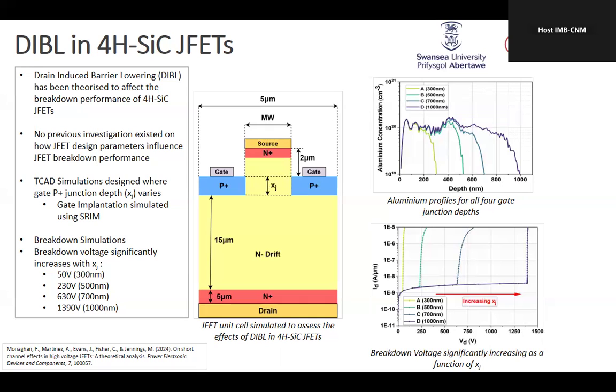Okay. So what you see on the right-hand side of the slide here, obviously we did some device design to analyze this, some SRIM doping profile. So this is a box profile for the P-type gates. And what we were doing, in the design phase, was varying the channel length here and varying the etch of the pillar. So again, the etch technology is really important, to get nice sidewalls. Much like a trench power MOSFET, for this type of device, etching is a key process, and control of that etch is very key.